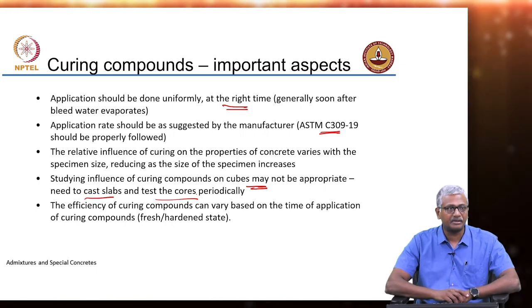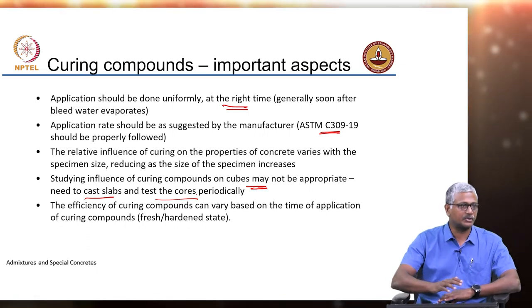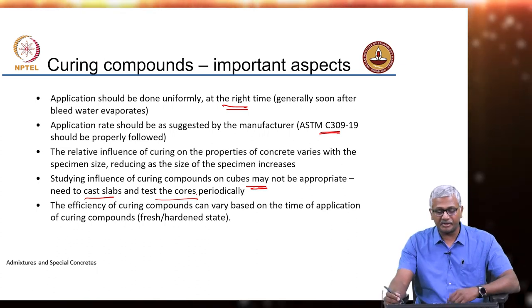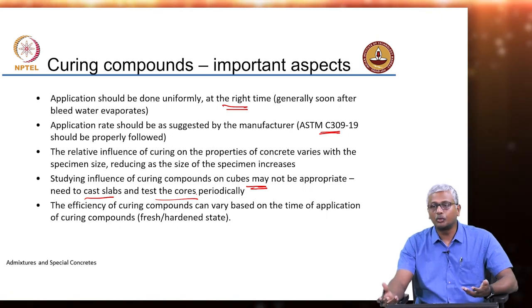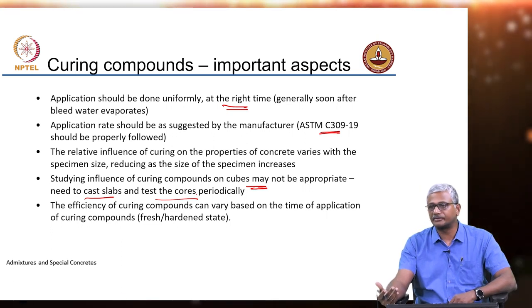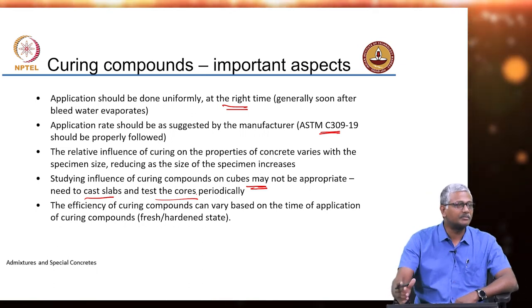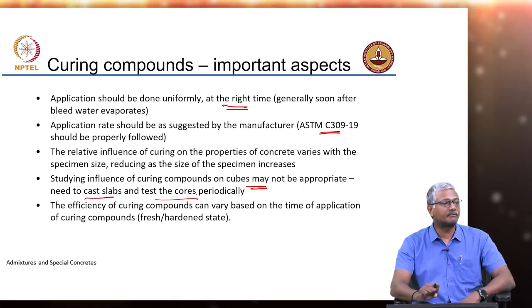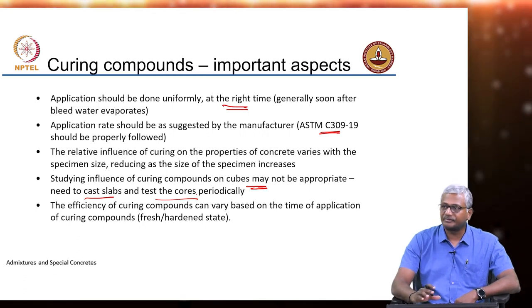The efficiency will depend not just on the specimen aspect but also on the type of compound being used. Efficiency can also vary based on time of application. In most cases on sites, people disappear after finishing the top surface and come back only the next day to start spraying water or curing. By that time, it is already too late if you are looking at modern concretes which have a high tendency for plastic shrinkage cracking. Applying curing compounds early enough is absolutely essential.